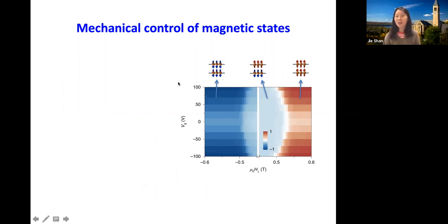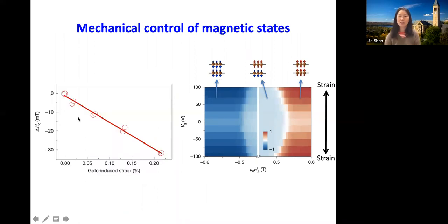The reverse effect also exists. So in other words, if you apply strain, you can change the spin flip transition field. Although the effect is relatively small, it's there. So you can think of an experiment like, if I apply a constant magnetic field sitting somewhere here, and then I change the strain by just applying the backgate, I can go from ferromagnetic to antiferromagnetic, and so this can be tuned.